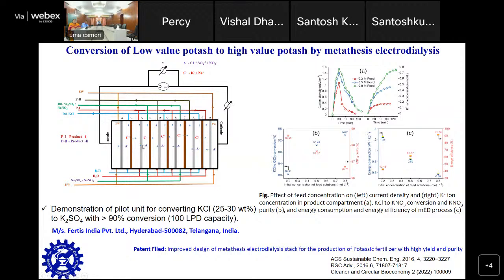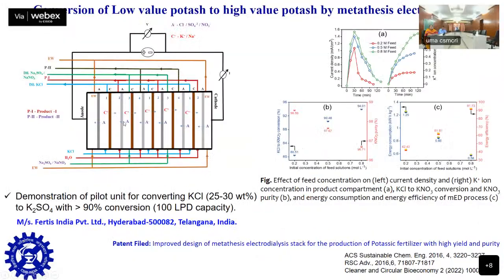crystallized salt can be produced. The purity of the salt was more than 99%, and we could convert more than 90% of the potassium chloride by this process. So we have signed an MOU with Fertis India Private Limited, Hyderabad, to convert that KCl to K2SO4, and we have to set up a 100 liter per day capacity plant at their site.